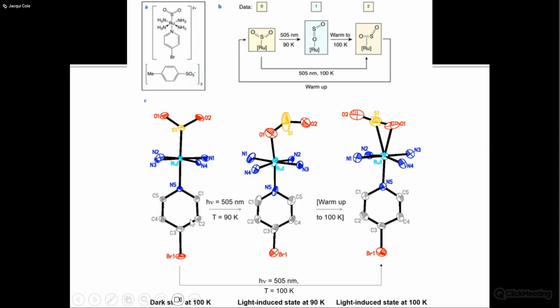In this case, for the first ever time in this series, this is the dark state at 100 Kelvin, but I managed to capture both the light-induced species, the oxygen-bound photoisomer, in 100% state. It's really hard to get these fully clean, to get the right temperature and the right light, 100%. So it's not disordered, right? There's no dark state left. 100% conversion in the oxygen-bound form.